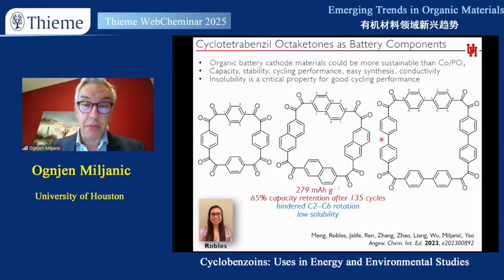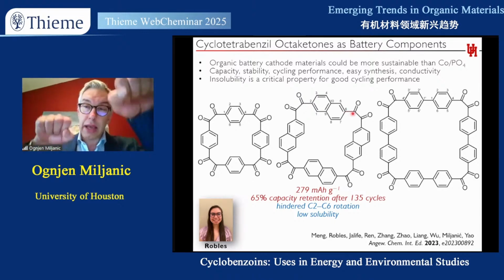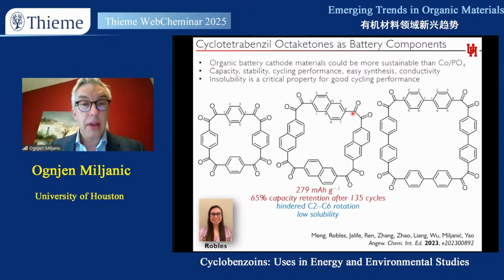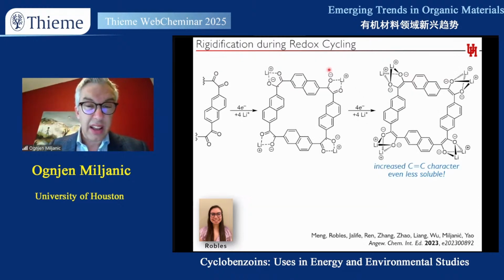Something similar can happen on the molecule on the right. In the molecule on the left, you have this C2 and C6 axes, which are offset from one another. And so the rotation would have to be a sort of bicycling motion, which is fine if you have an acyclic molecule. But in this cyclic molecule, one of these bicycling motions cannot occur independently. It has to be coupled at least with the motion on the other side of the ring, and possibly with all 4 rings. And this leads to entropically unfavorable rotation. And so because of that, this molecule is the most rigid one. It is low in solubility, and it stays so as we go to reduced states.